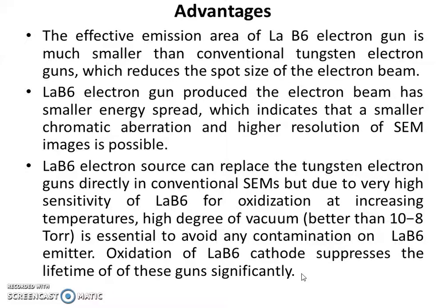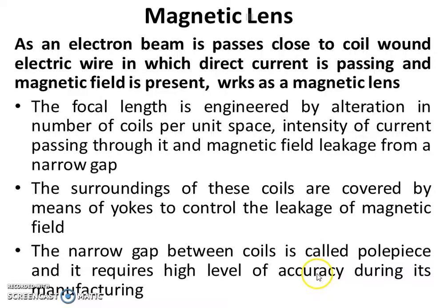Apart from all these, the LaB6 electron source can directly replace the tungsten electron gun in a conventional SEM, from a modification point of view. But due to the very high sensitivity of LaB6 to oxidation at increasing temperature, a high degree of vacuum, nearly 10 to the power minus 8 torr, is essential. In the absence of this vacuum, LaB6 electron guns are not useful due to the effect of oxidation, which reduces the lifetime of LaB6 electron guns.